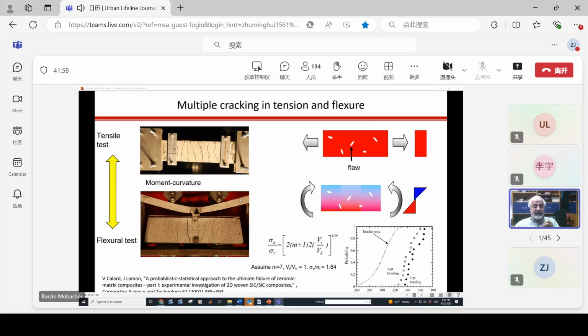So here is basically a flexural specimen, and we put a mirror at 45 degrees so we can stand in front of the specimen and see the number of cracks that have formed. And we see that we have more cracks in tension than in flexure. Of course, it has to do with the fact that the volume in flexure is much smaller. We can use a Weibull approach to show that because the representative volume in tension is much larger, the probability of flaws is higher. So that's one way to explain it.